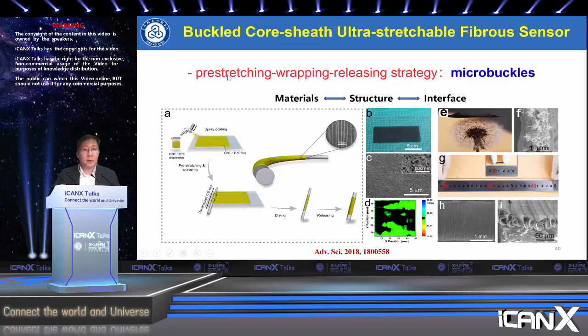And with these films, we use the pre-stretching, wrapping and releasing strategy. After we get the carbon nanotube and thermoplastic films, we use pre-stretched thermoplastic wires, and then we wrap these films on these bodies. After we release, we can get ordered microbuckles on its surface. And this surface can make the buckled core-sheath, ultra-stretchable fiber sensors.